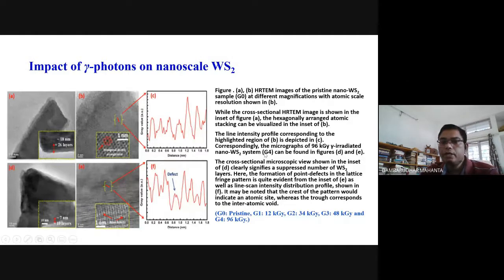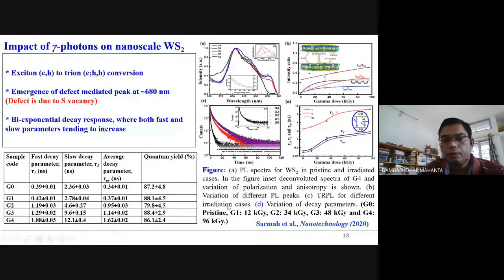So in fact, we have studied gamma radiation considering different radiation doses, G1, G2, G3, G4, as it is mentioned here. So G0 is kept as reference, which is pristine. Then G1 12 kilogray, then 34 kilogray, 48 kilogray, up to 96 kilogray. Now, the optoelectronic properties, what we have investigated in this particular work is that, first of all, when you excite these samples, all these 4 samples, unirradiated and gamma irradiated samples, you see that there is a